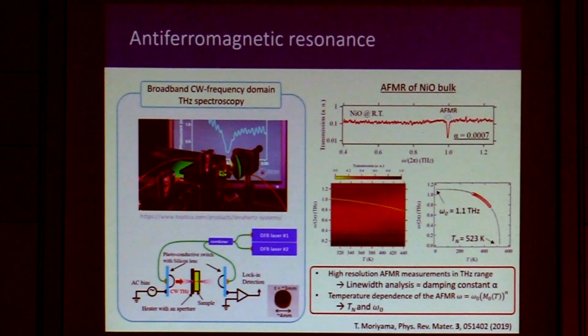First of all, I would also support the comment that nickel oxide has this biaxial anisotropy, and from naive theory it should have linearly polarized modes, which shouldn't contribute to the spin current. But on the other hand, what is the size of your spherical particles, and can you exclude that you have a surface magnetization which contributes to your signal? You excite some modes, some oscillations of the Néel vector, but due to the coupling of surface magnetization with the Néel vector, you can have spin current which originates simply from these non-compensated moments.